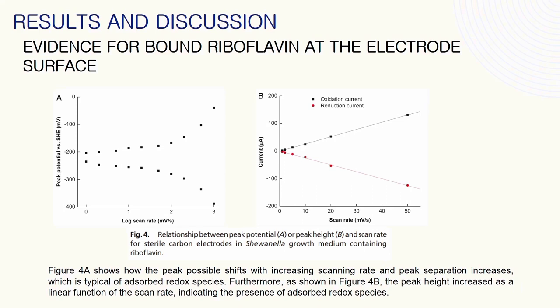The peak potential shifts with increasing scanning rate and peak separation increases, as seen in Figure 4a, characteristic of adsorbed redox species. Moreover, the peak height increased as a linear function of the scan rate with R square equal to 0.999, as Figure 4b shows, another indication of adsorbed redox species.